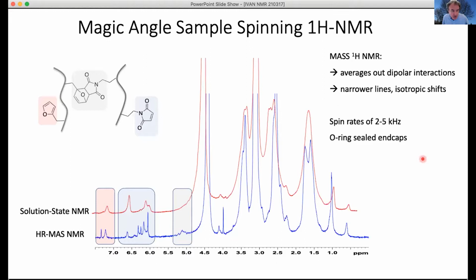When we apply that to our current system, the spectra are not quite as clean, but we can follow the disappearance of the two functional groups shown here over time. I compare a solution NMR with a magic angle spinning NMR, and we can see the appearance of the cross-linking site. We also see other peaks more highly resolved, such as here and down here as well. This helps us figure out what is going on inside the gel.